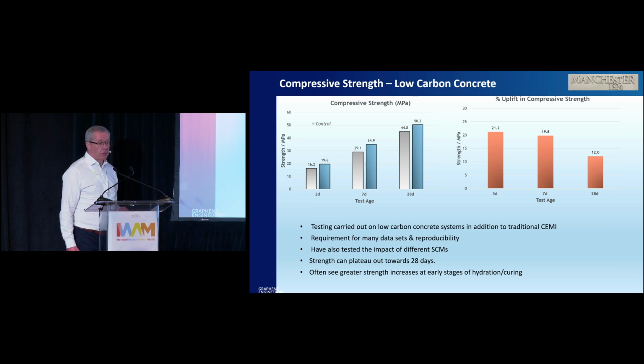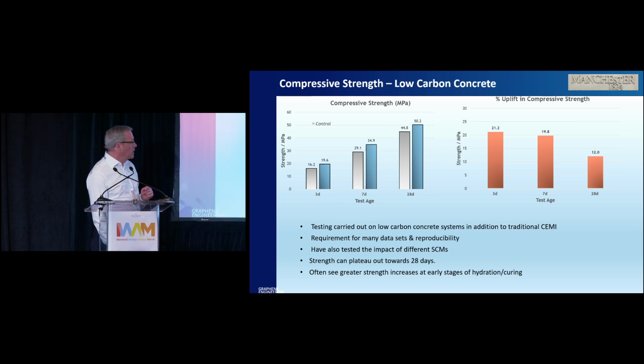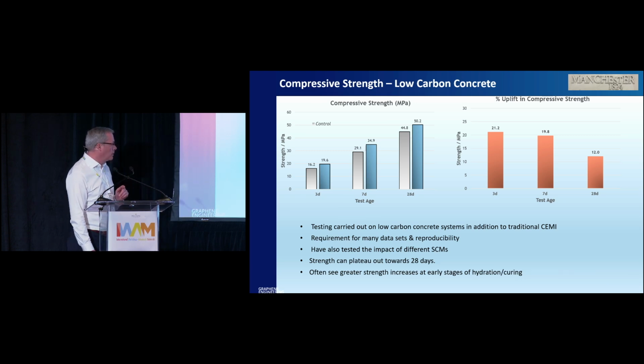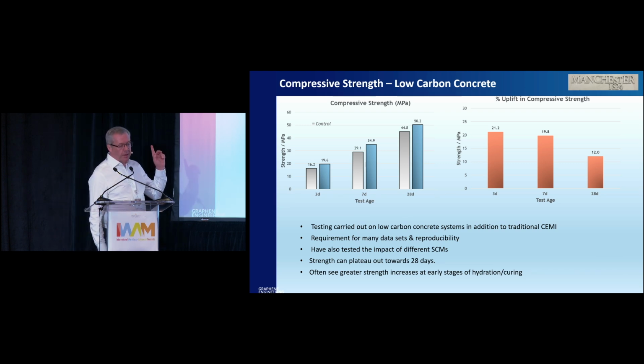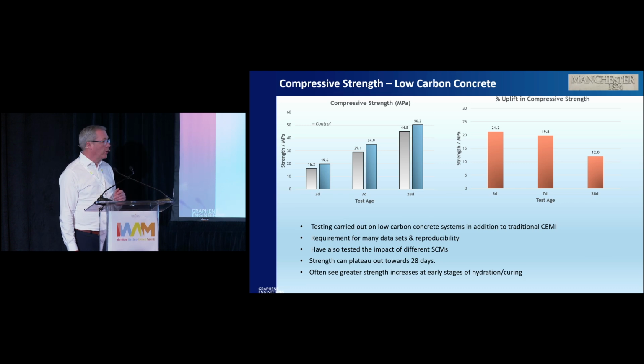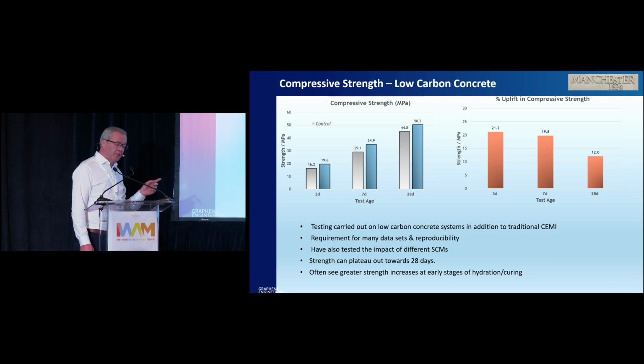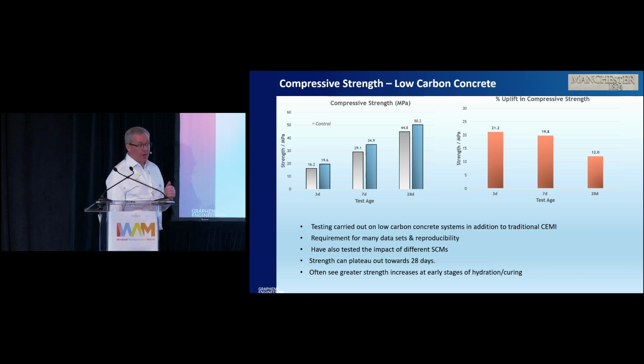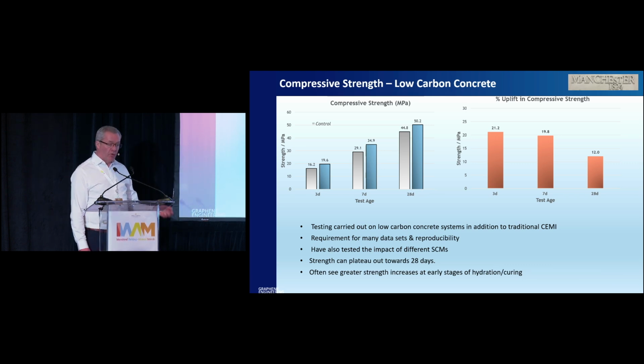And we can also control things like water, crack propagation and early-day hydration. I'll give you some data, but the key thing is the early-age strength. Now, if you look at the dispersion of dry powder systems, this consistency is much more difficult to achieve, because you're dealing with such low volumes in a large volume dry mix, and it's fairly difficult to get that consistency.